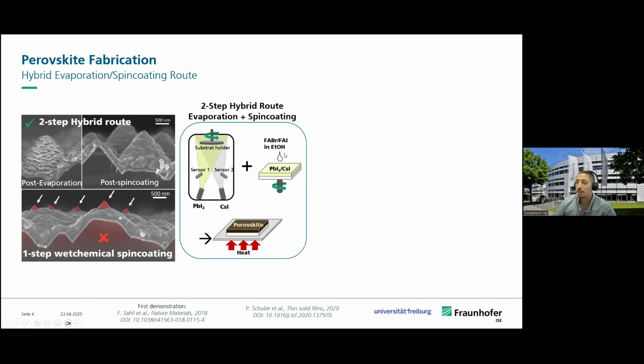And in the second step, we infiltrate the organic parts of the perovskite precursors within this scaffold. So you can think about this as a sort of sponge that will absorb these organic precursors. And after an annealing step, we have a conformal coating on textured silicon. Now, as you can see, there are really 3 different steps, and for every step, there are a lot of parameters. So it opens up the space for a wide parameter variation, and every parameter can play a critical role in the final perovskite film.